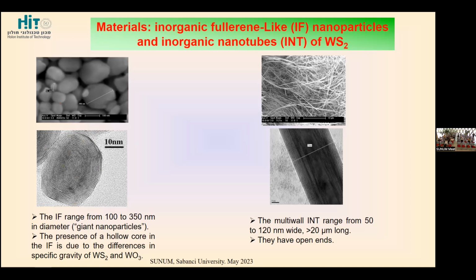In the case of nanotubes, these are multi-wall, quite long nanotubes of up to 20 or even more microns long, and their widths range from 50 to 120 nanometers. They also have open ends, so there is some possibility to introduce species from their ends and also through the defects.